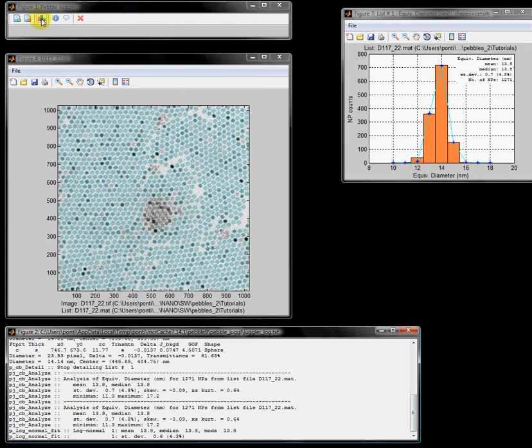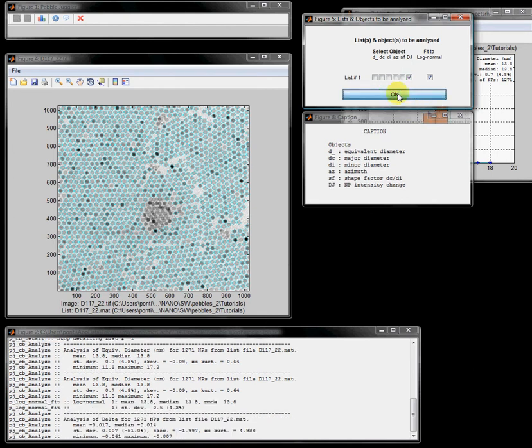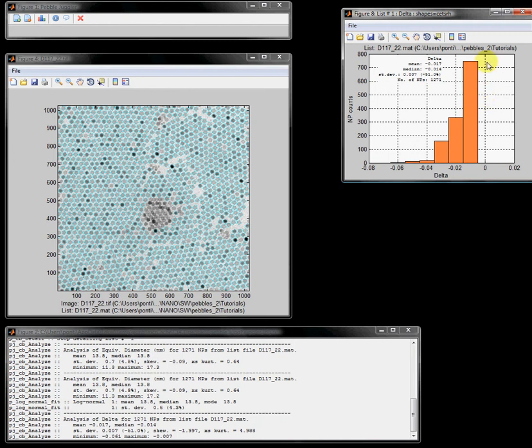Last, I would also like to show you the distribution of the nanoparticle intensity change. And you can see all the values are, of course, negative. Most of the values are on the high side, meaning closer to zero, which represents nanoparticles scattering mostly by mass thickness mechanism, and a minority of highly scattering nanoparticles which are close to the Bragg diffraction scattering.